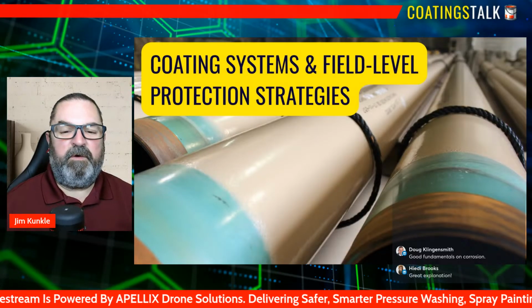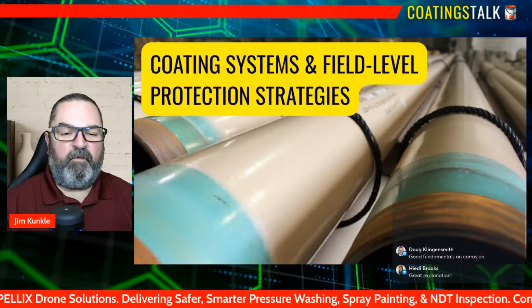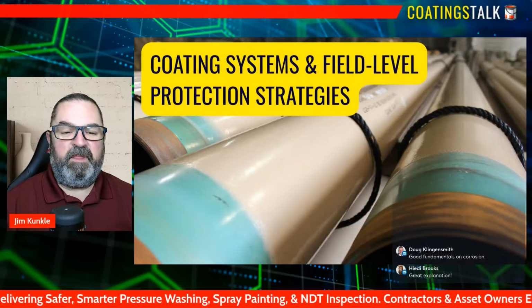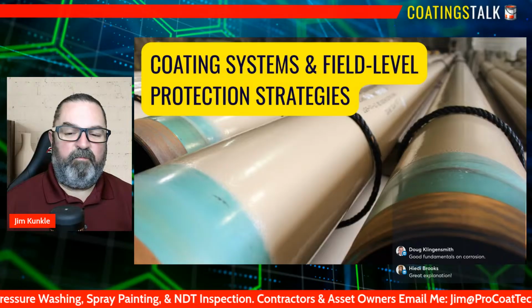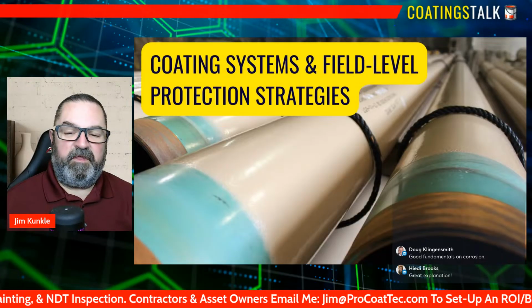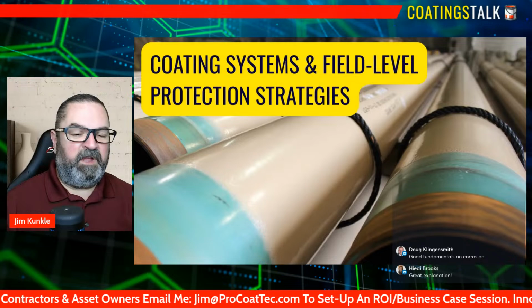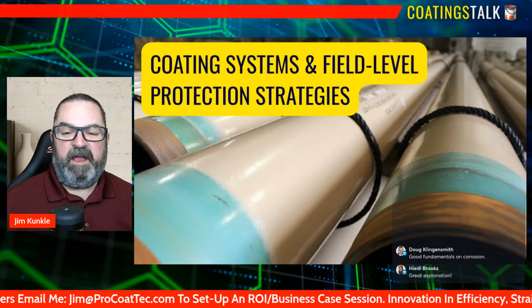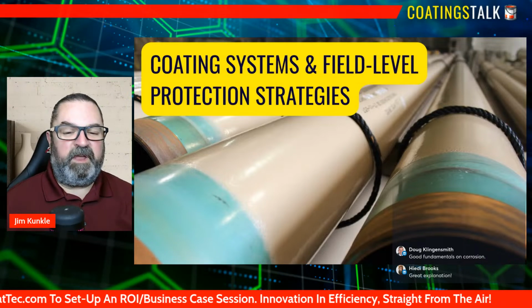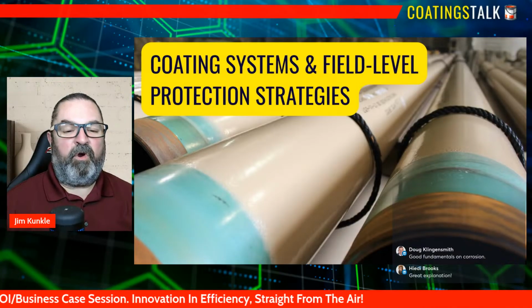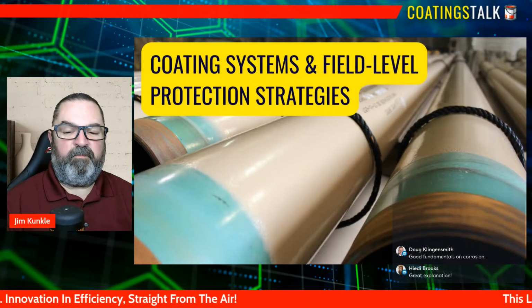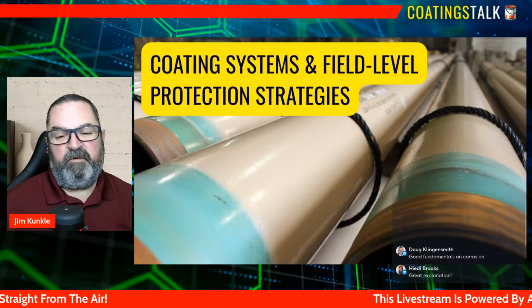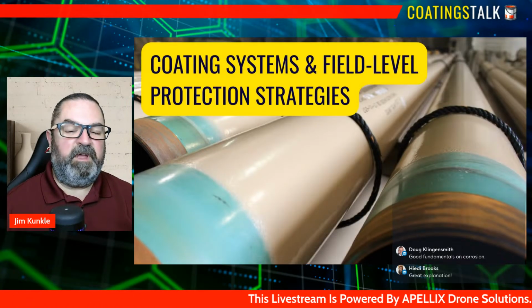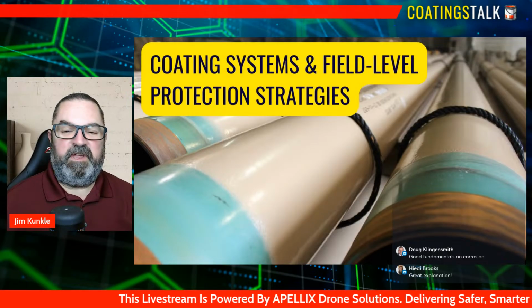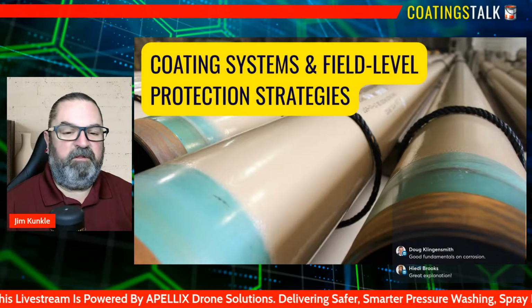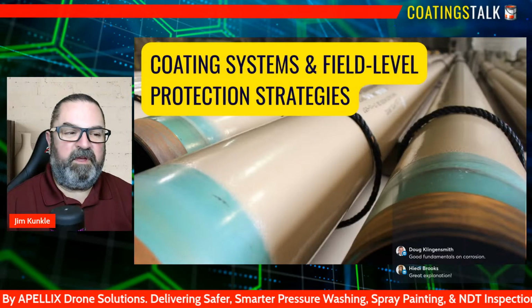Film thickness is equally critical because coatings are engineered to perform within a specific thickness range. Too thin and the coating lacks the barrier strength needed to keep moisture, oxygen, and contaminants away from the steel. Thin spots often occur on edges, welds, and complex geometries, exactly the areas that are most vulnerable to corrosion. Too thick and the coating may crack, trap solvents, or cure improperly, and this leads to premature breakdown. Achieving uniform, verified film thickness ensures the coating system delivers the protection that it was designed for, especially in immersion or high-stress environments. Cure time completes the equation.